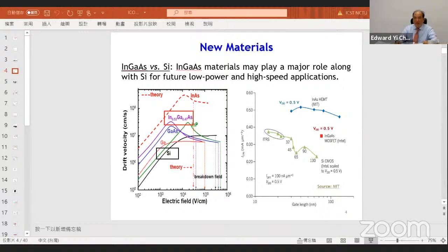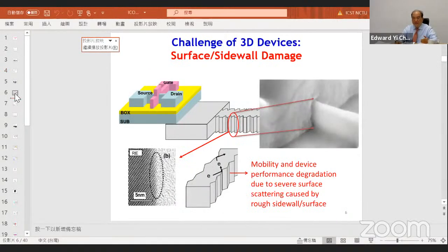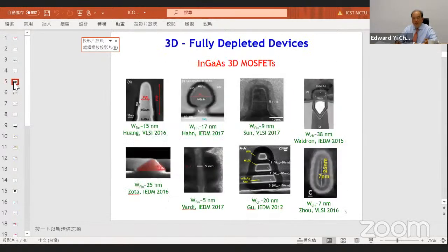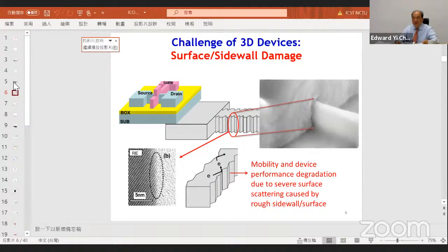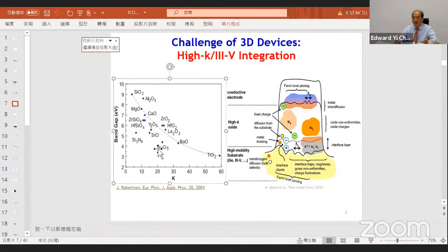And one of the biggest challenges in the past for the III-V MOS application is that III-V material and the capacitors have a lot of interface traps. It means that if you use high-K material on III-V material, the interface has a lot of traps. So in this study we follow the silicon technology. We use high-K material, but again we have to solve the interface problem, and the oxide has some border traps, and the interface has many interface trap defects.